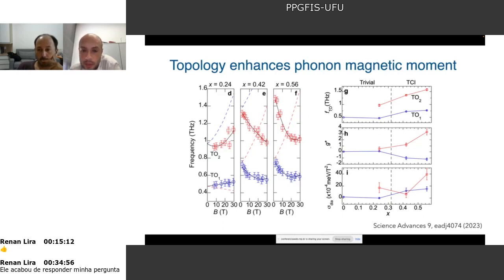And let's look at this one here, which is the most relevant for this talk. You can see here this dashed line is the frontier between trivial and topological phases. And when you increase X, you see that the magnetic moment is very small, but then in the topological phase it is very large, right? This, for both phonons, increases a lot, 2 orders of magnitude. So we can say here that somehow topology enhances the phonon magnetic moment.